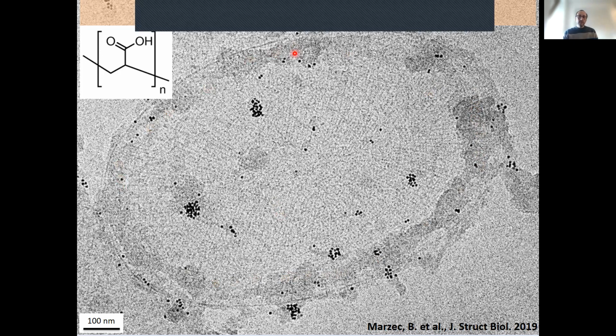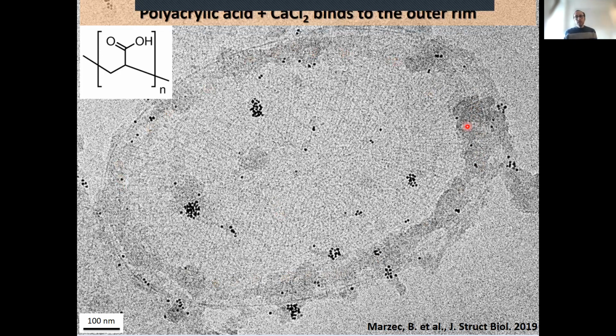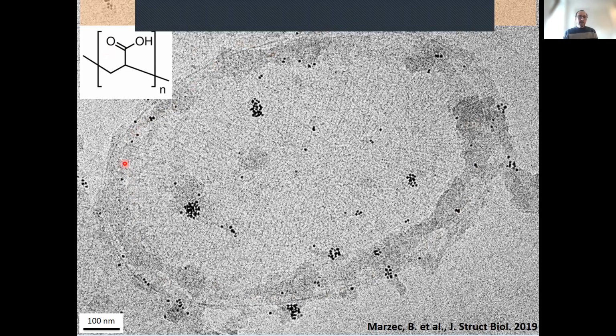And what this is telling us is that if we take a polymer, that the only thing it has in common with the polysaccharide is the charge, the amount of charge residues, and we can get it to bind to the rim of the base plate, it means that the interaction is not specific, that it's something else. And that something else must be simply electrostatic interactions. So we have a highly negatively charged complex, even in the presence of calcium ions. And that means that the rim of the base plate must be positively charged.